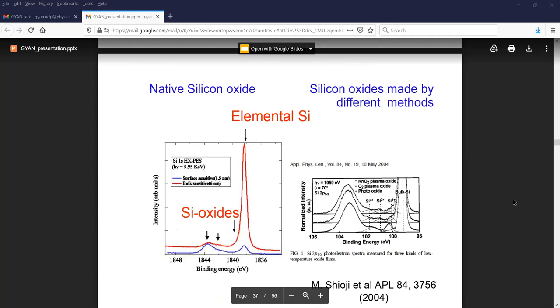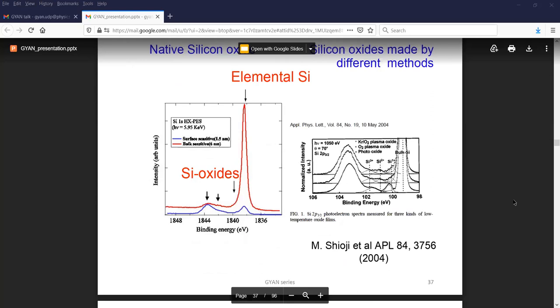This is an example of how one can use photoemission to measure silicon, a semiconductor. Depending on the binding energy, you can distinguish between elemental silicon as well as oxides, which will have higher binding energies. On the right side figure, you have bulk silicon, and you can actually trace back silicon 1+, silicon 2+, silicon 3+, and silicon 4+ which is SiO2 — they have distinct energies. You have tables with these numbers, and you can check the valency of the sample that you're measuring.